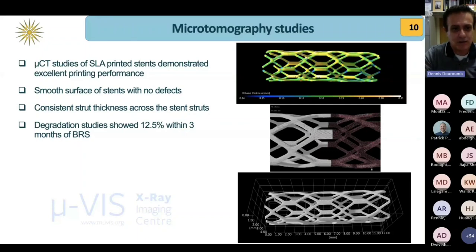This is very important. We also ran some degradation studies, and we saw that for the resins we designed ourselves, or tried to develop, there was a degradation of about 12.5% over 3 months, and this was also really good because those stents are supposed to be mechanically strong for at least around 24 months before they start degrading completely in the body. And also by that time they will be fully covered by endothelial cells, so there's no cracking or breakage of the stent that will go into the blood circulation.